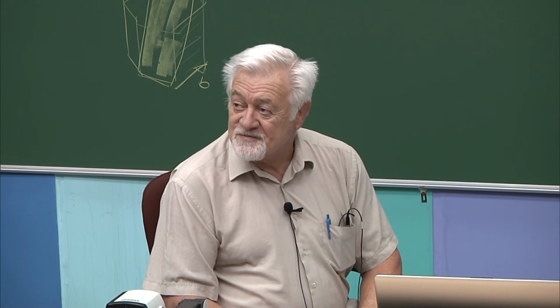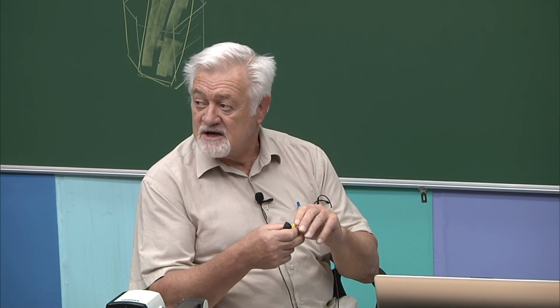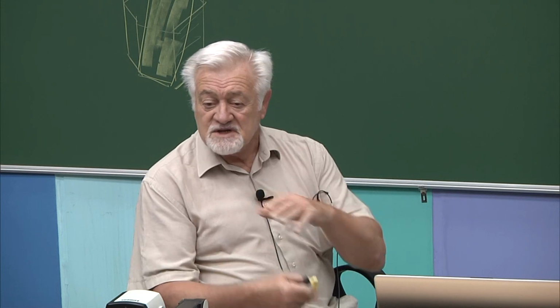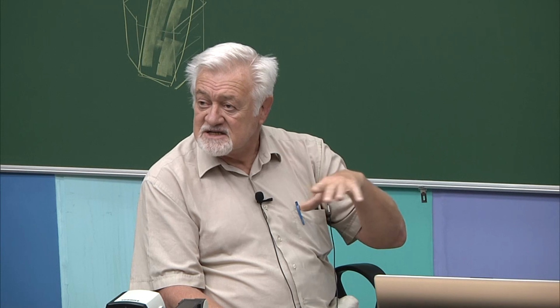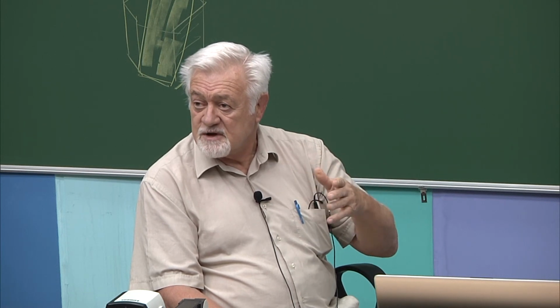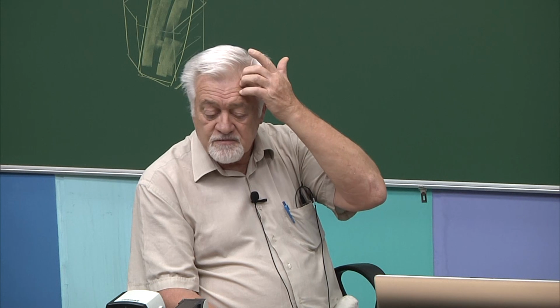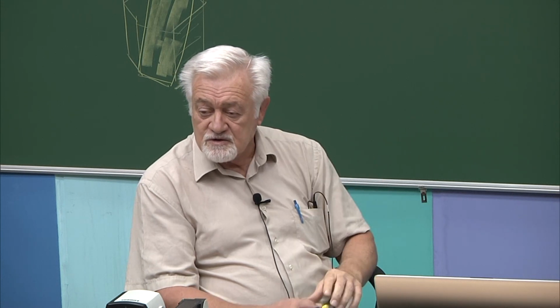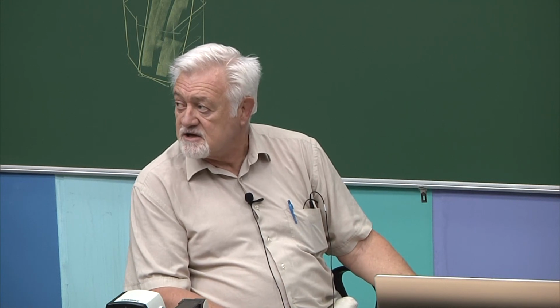And so, as slip becomes easier and easier because it is a thermally activated mechanism, the twins have a relatively flat critical stress, but the slip systems have a strong dependence on temperature. As the temperature increases, the critical stress to move them is lower and lower. So the reason for the twins to disappear is because slip is much easier in general in all materials at high temperatures.